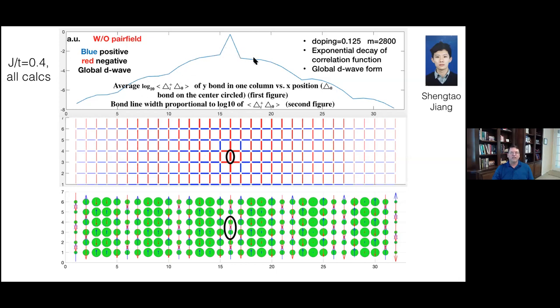So this curve here, which is decaying more or less linearly, is showing exponential decay. The values are getting very small towards the edge of the system. So this is showing a system with a very weak response at this particular filling of 1/8, where the stripes really seem to be the strongest.